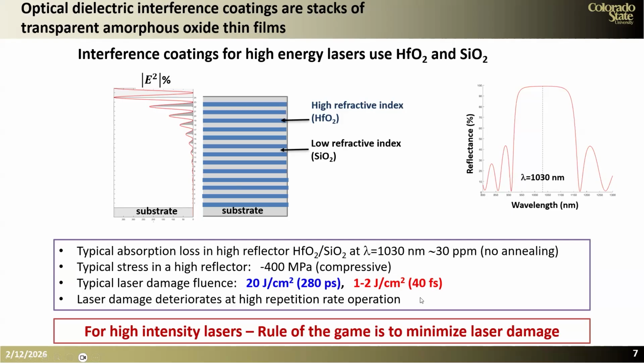But when we go to 40 femtoseconds, then the laser damage fluence decreases significantly. So for high intensity lasers, the coatings that we develop have to have the highest possible laser damage performance. And if we go to very short pulses, we also have to take into consideration that the bandwidth of the mirror, for example, has to be sufficiently large to propagate this 40 femtosecond pulse.